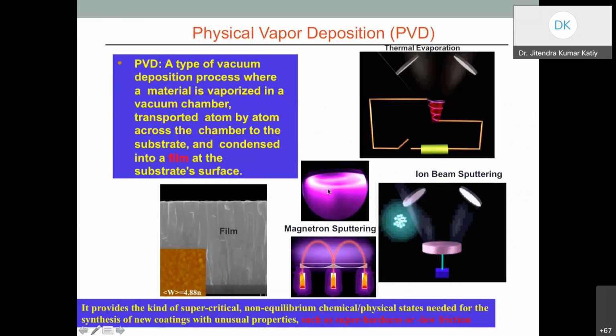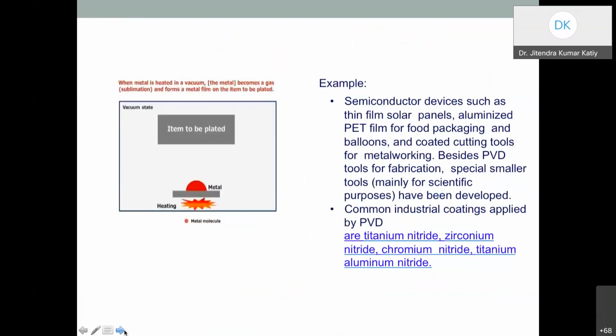So physical vapor deposition, further we enhance these things. Here you can see how you can do the heating by induction coils. We heat and deposit the film over the substrate, and we can see the AFM image and find that the thickness is approximately 4.8 nanometer. A very thin surface we can adopt by this physical vapor deposition. Even titanium nitride, zirconium nitride, chromium nitride, you can physically vapor deposit over any substrate.